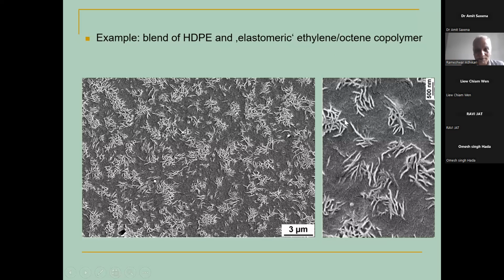So in the higher magnification, you see these so-called lamellae. You can see that some of the lamellae are 500 nanometers to 2 micrometers long. You can estimate that with the help of this scale bar. And this area, which does not show any crystalline region, is ethylene octene copolymer. We can wonderfully see that the high density polyethylene part is dispersed very nicely, uniformly in the matrix of elastomeric ethylene octene copolymer.